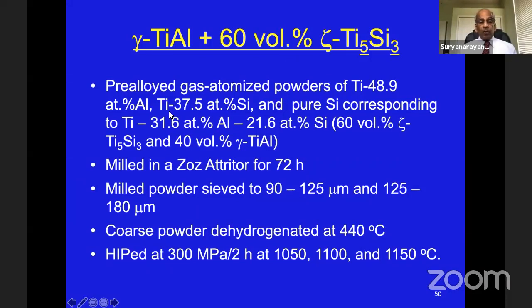So we took mixtures of titanium 48.9 aluminum corresponding to this, titanium 37.5 atom percent silicon, but this is not exactly this. So we add extra silicon to produce this particular composition, which corresponds to 60 volume percent of the titanium silicide and 40 volume percent of the titanium aluminide. That means this is basically a titanium silicide based composite containing titanium aluminide. So we mill the powder, we sieve the powder to different sizes. The coarse powder is dehydrogenated at 440 degrees and then subjected to HIPing, hot isostatic pressing at 1050, 1100 and 1150 degrees Celsius, and studied the microstructure.